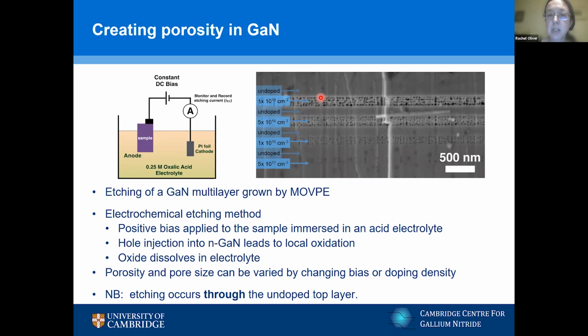These porous layers are separated by undoped layers, which tend not to etch. And you might look at this and think, okay, they've made a gallium nitride sample, they've cracked it open and provided an exposed surface for the etchant to access the pores. We etched the sample and then cracked it open so we could see the pores. The etching here is coming through the undoped layer, which appears intact and unetched. I'll explain how that happens in a second.